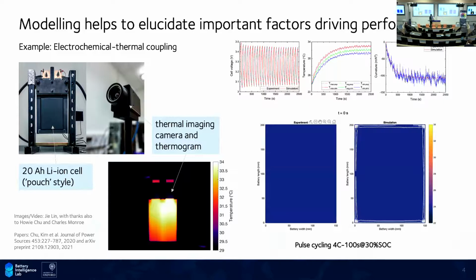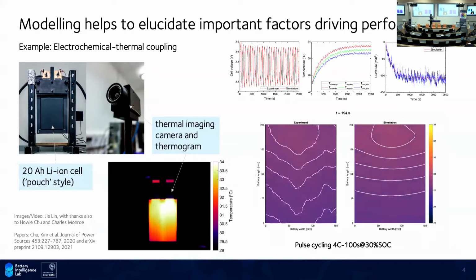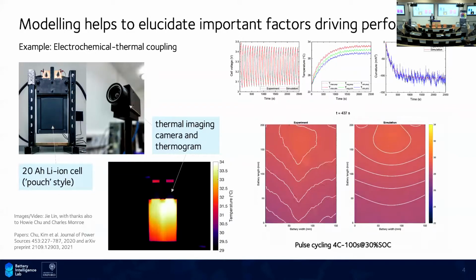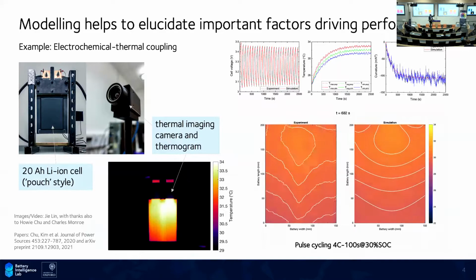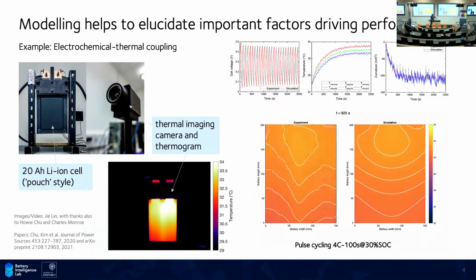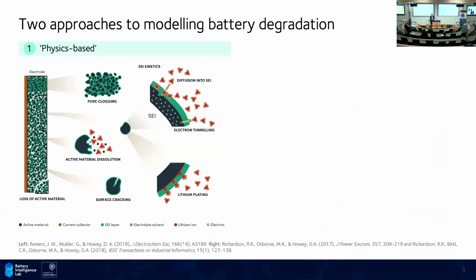So if I show you a video of what this looks like, this is actually a video comparing experiment on the left and simulation on the right. Not the most exciting video in the world, I'll give that to you. But what you can see is that the hotspot gradually forms, moves down away from the tabs. And there's also this kind of breathing effect, which is quite interesting. So that's what these little wiggles correspond to. And that's related to reversible heating and cooling in the battery. Why is this interesting? Well, it turns out that if you take a slice through the temperature of this thing, the curvature in the horizontal direction is directly related to the diffusion time in the solid materials underneath. So you can start to find out stuff about micro scale effects just from a macro scale temperature image.